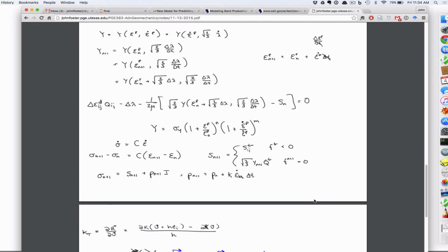But if we are comparing this point to the previous stress, it might be less, but it's actually still on that surface? That would be the case if delta lambda was 0, right? Then it would remain where it was. Because the yield surface, in this model and in most models, doesn't shrink. It only grows.